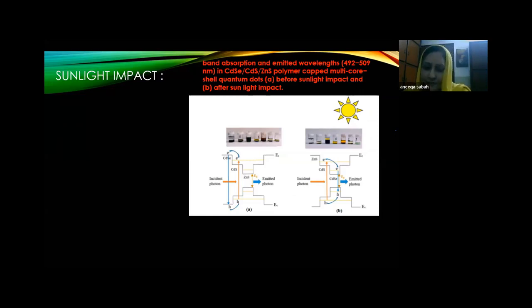Due to this degradation, we observed that the incident photon was absorbed by cadmium selenide, then there was an excitonic transition for electrons and holes. They tried to recombine, and after recombination, they emitted photons, and their emissive properties were observed.